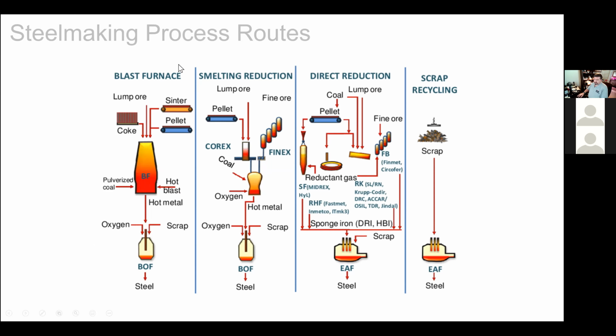It utilizes a blast furnace into which we feed coke, lump ore, sinter, or iron ore pellets. And we feed those into this shaft furnace. We blow hot blast, which is hot air, which might be oxygen enriched, into that vessel. And along with pulverized coal, this was a technology developed to reduce the amount of coke required and basically substitute other carbon for the coke. And that allowed people to reduce the amount of coke they were using in the blast furnace by about half. But the coke provides not only a metallurgical purpose, but also a structural purpose because it helps to support the burden, all of these materials that you're feeding into the blast furnace.